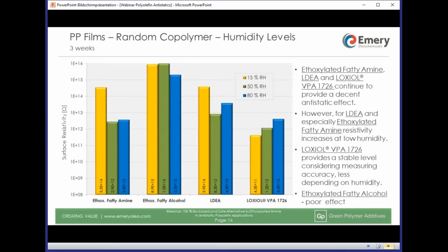Same films, but now we are checking the influence of humidity. Ethoxylated fatty amine, LDEA, and LOXIOL VPA 1726 show a good and relatively similar performance. However, looking only at the yellow columns, we see a slight tendency for LDEA and even more for ethoxylated fatty amine that resistivity increases for low humidity. Ethoxylated fatty alcohol, as seen on the previous slide already, does not show an effect.